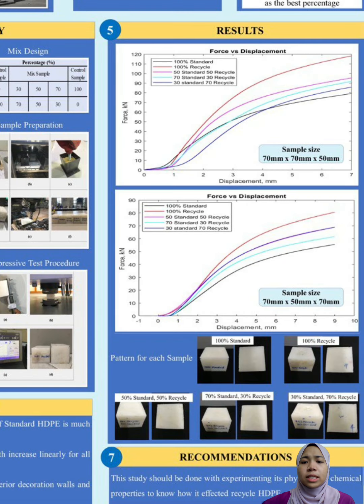Now we will go for the result and analysis of the experiment. The result of the experiment showed the compressive test on the force and the displacement for 2 different sizes, which are 70 mm times 70 mm times 50 mm and 70 mm times 50 mm times 70 mm. For a sample size of 70 mm times 70 mm times 50 mm,